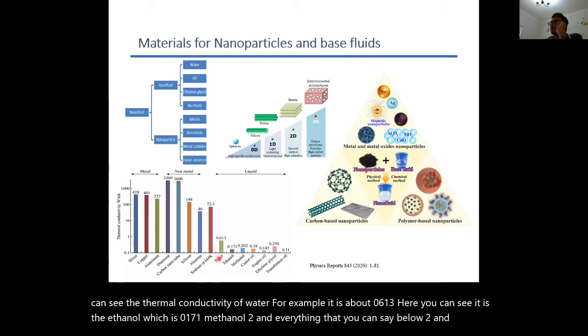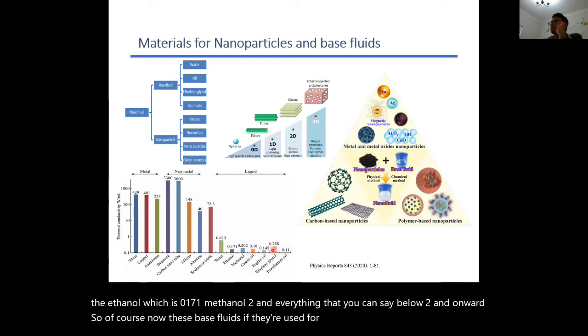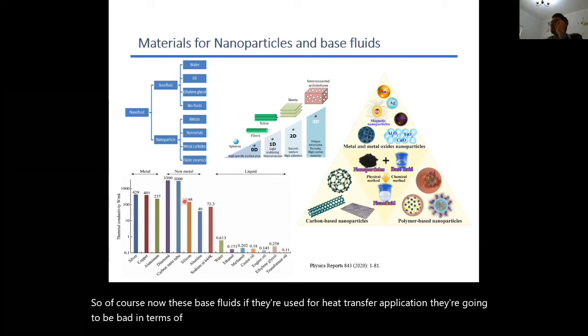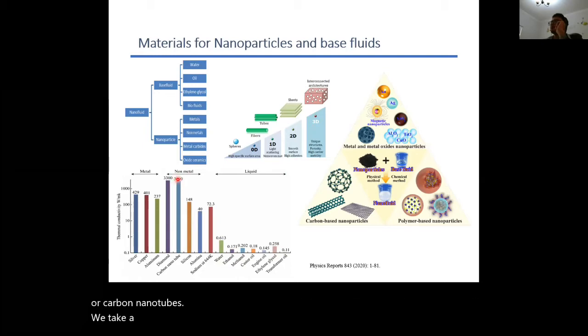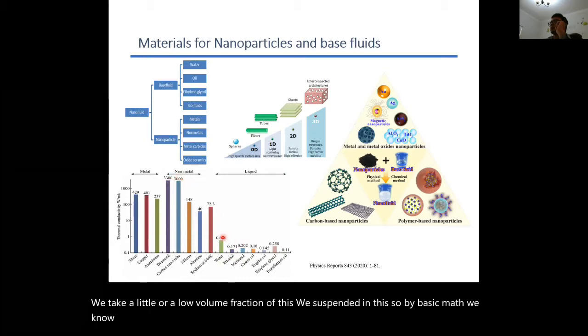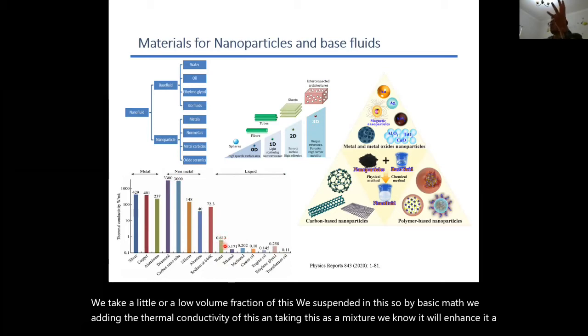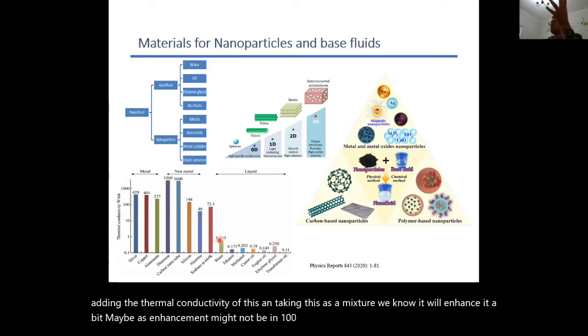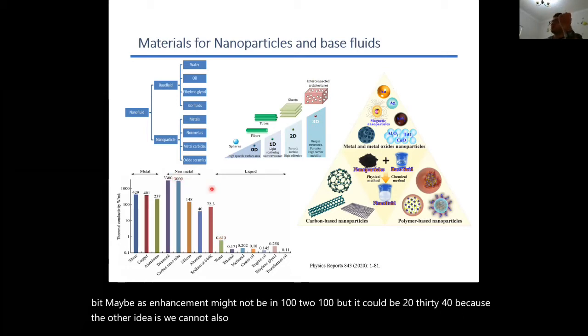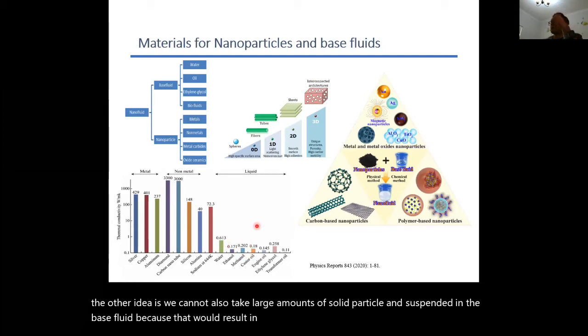So of course, these base fluids, if they're used for heat transfer applications, are going to be bad in terms of thermal conductivity. So what you do is, for example, take diamond or carbon nanotube. We take a low volume fraction of this and suspend it in the fluid. By basic math, adding the thermal conductivity of this and taking it as a mixture, we know it will enhance it a bit. The enhancement might not be 100% or 200%, but it could be 20, 30, 40%. We also cannot take a large amount of solid particles and suspend it in the base fluid, because that would result in negative impacts such as pumping power and pressure drop, and it will not be a liquid anymore. It might be an emulsion.